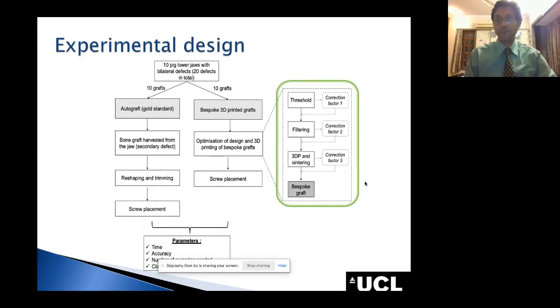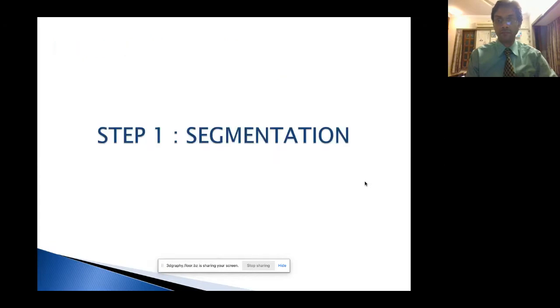And for this, we decided to create 3 correction factors in the process. Our experimental design basically took into account 10 lower jaws with bilateral defects, so 20 defects in total. 10 were done with an autograft performed by Federico, and 10 were done with a bespoke 3D printed graft, also done by Federico. And the process was optimized. I will just present it now.